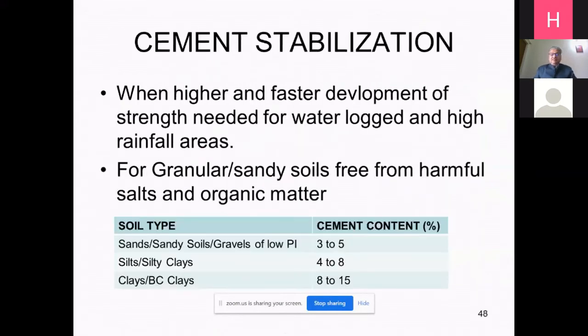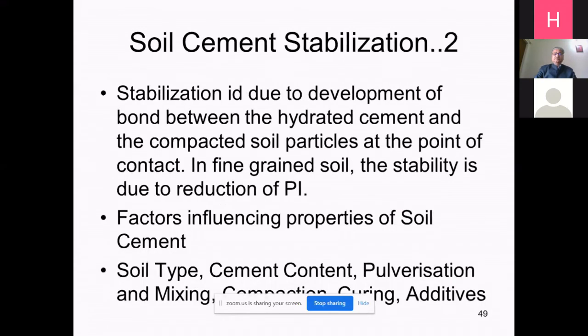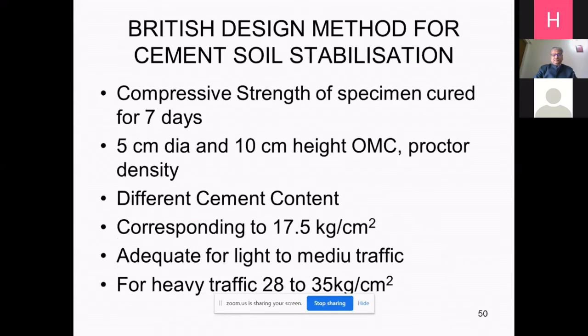Then you have the cement stabilization. If you are not able to get the result from the lime fly ash also, then you can go for cement stabilization. Cement is 3 to 4 times more costly than lime. But when higher and faster development of strength is needed, then you go for this, especially in waterlogged areas or high rainfall areas. If you want to use lump sum values, then these are given here. Otherwise, you can go for the method.